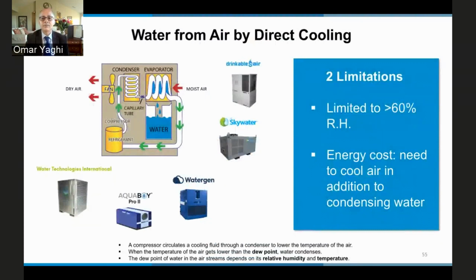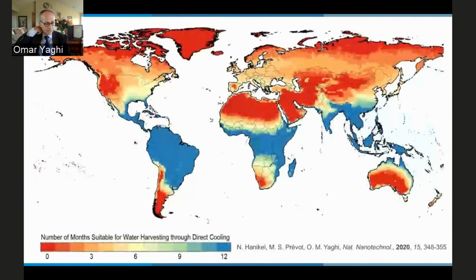Now, the idea of harvesting water from air is not new. It's been around since time immemorial. And in fact, you could buy instruments that allegedly take up water from air. They claim that they can take it up regardless of the weather, but in fact, they only work at humidities higher than 60%. The rest of the time, or the rest of the humidity range, they don't work. At lower humidity, where it's most needed, these do not work. The reason they don't work is because in order to get water using this equipment, they rely on direct cooling of air. And I'll explain that in one second.